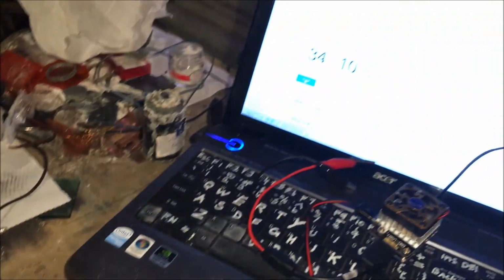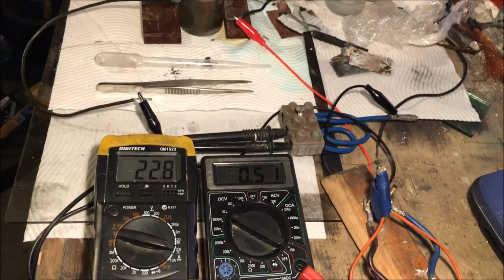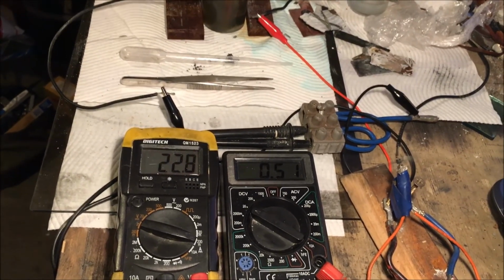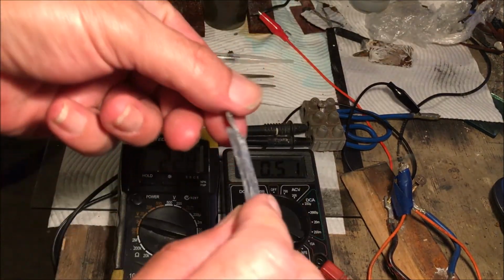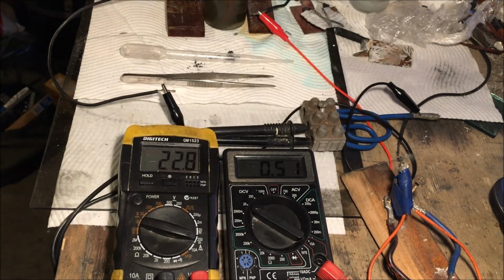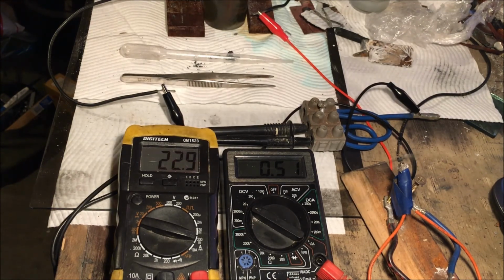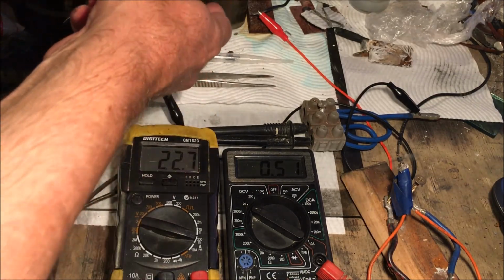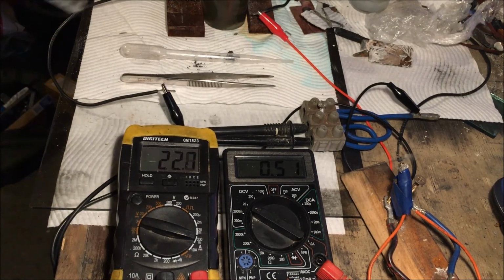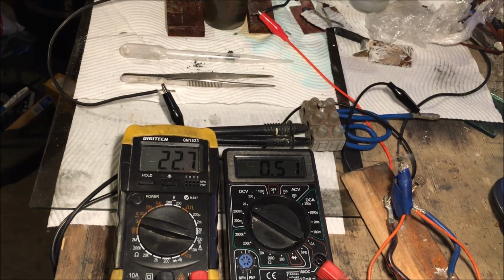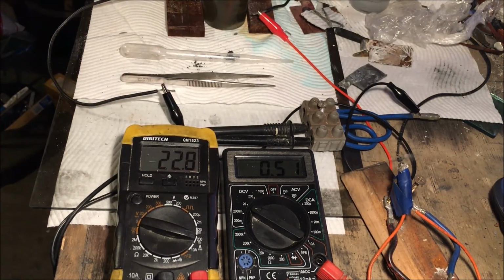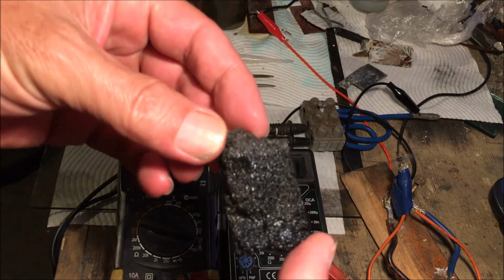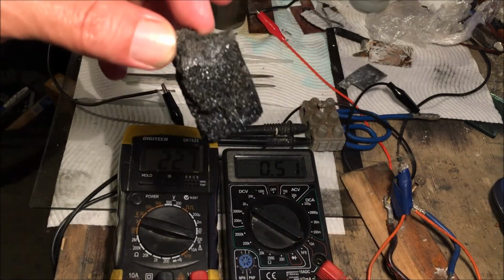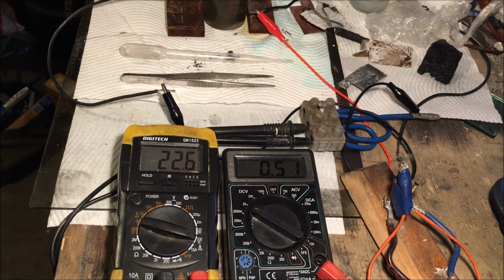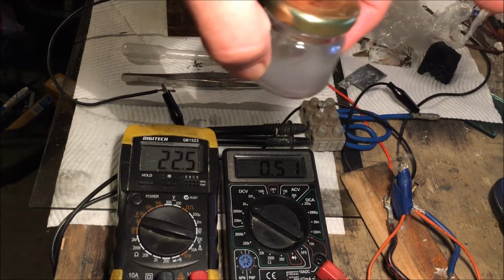Okay, it's a half-hour run time so far, and we're still at 0.5 volts, so the copper cell is holding up really well with the zinc and carbon. In fact, it's performing the same as a plate of zinc. So the copper electrodes already had the 20 charges with the other zinc cell, which got consumed. So I'm thinking, because it's in the carbon structure, it should stay in there and we should be able to achieve a few more charges, maybe. And we're still at 0.5 and 22 milliamps. That's not too bad, really. It's a bit better than just plain carbon. So the next story is to coat this with some copper with electrolysis. I'll do the small one first. Also want to see if urea in the mixture is going to do anything.